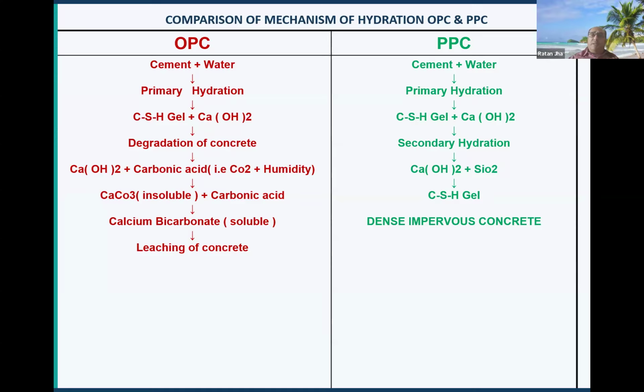It is not reused. In OPC, that calcium hydroxide reacts with carbonic acid from the environment. Humidity plus carbon dioxide converts it into calcium carbonate, which is insoluble. Once again, in combination with carbonic acid, it forms calcium bicarbonate, which is soluble in water, and leaching of concrete starts in terms of efflorescence. That leaching makes your concrete more porous and more vulnerable, and this is one of the main reasons for reinforcement corrosion at early ages. Very early ages, I can say within 2 or 3 years of construction of your bridge